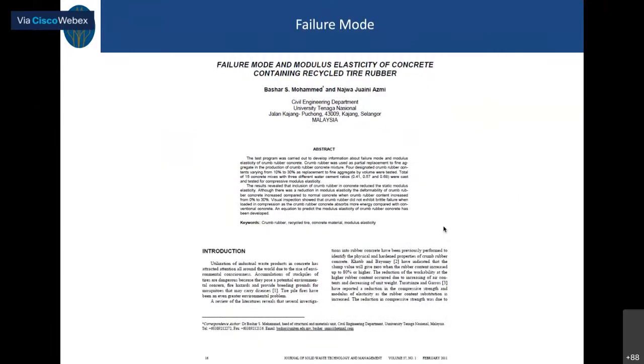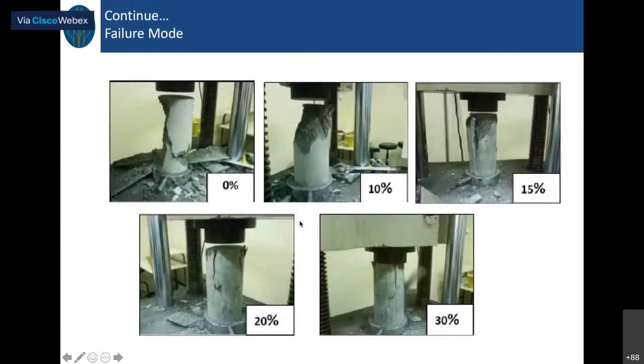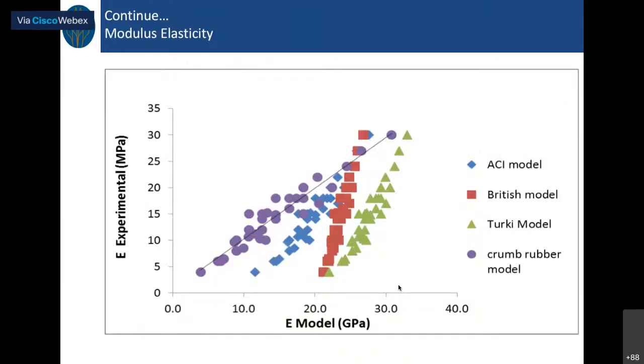You just email me. And the failure mode is very interesting. You see the failure mode when we don't use crumb rubber, 0%, and when you increase the crumb rubber up to 30%, you see this failure mode. It's an intact one, so it's very good in areas prone to earthquakes or cyclic loading. Also, this one shows that the formulas for modulus of elasticity available in the ACI code, the British code and the Turkish code cannot really be used for rubbercrete. That's why we created a new formula to find the target modulus of elasticity.